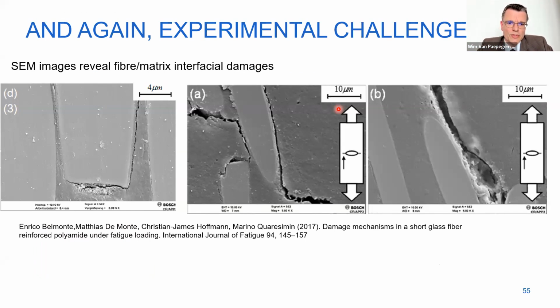So you need to write a proposal. It takes a long time, and then you get a few hours of beam time on a synchrotron, and there you could start to see these things in situ. But what I would really hope for, but I think it's technically very hard, is to get such things more to the lab environment, so that you could follow damage mechanisms in real time, not post-mortem. Also, the mechanisms that I showed you for the ply cracking are observed from the edge of the sample, not in the volume.